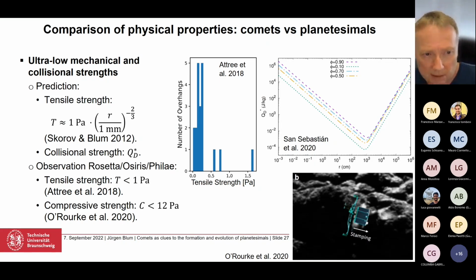But the measurements were basically by the paper of Attree et al. That the tensile strength, from the cliff collapse and other things, can be estimated to be indeed below 1 Pascal. So you're seeing a histogram here of the measured tensile strength by Attree et al. 2018, and you see the bulk of the data is even below 0.5 Pascal. So that speaks in favor of pebbles being present, first of all, and second, pebbles being larger than millimeters in size.